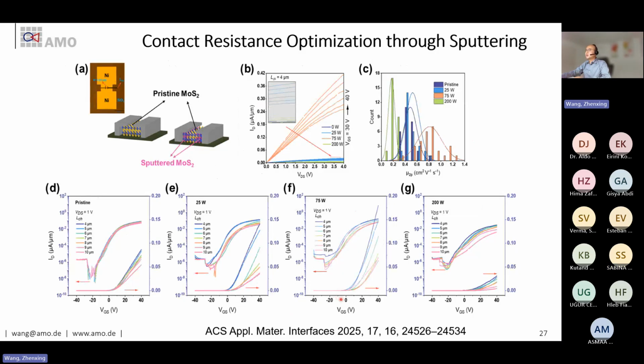And this, I think, is my last slide in this section, where we try to use plasma treatment for the area that we want to contact on MoS2. Basically, you see this is a normal transistor that we contact directly with nickel, the metal. But this is what we propose. We sputter the area that we want to make the contact with argon plasma. So it's somehow also plasma treatment. But here we have proof to show that this also actually modifies the phase of this material, so we form directly a heterojunction here, and this phase is better for contacting. It's a rather metallic phase. So that's what we call a structural modification through sputtering. So with this, we can also improve the contact resistance.